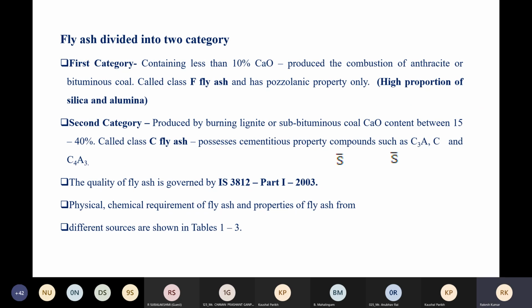Now, fly ash is a finely divided powder, as we have already told you. In the first category, containing less than 10% CaO, calcium oxide, produced by the combustion of anthracite or bituminous coal, it is called class F fly ash and has pozzolanic property only. A high proportion of silica and alumina is available in this. Second category, produced by burning lignite or sub-bituminous coal, CaO content is more, between 15 to 40%, called class C fly ash, possessing cementing properties, with compounds such as C3A and C4A3S. So here, class F fly ash is used mostly for construction purposes.